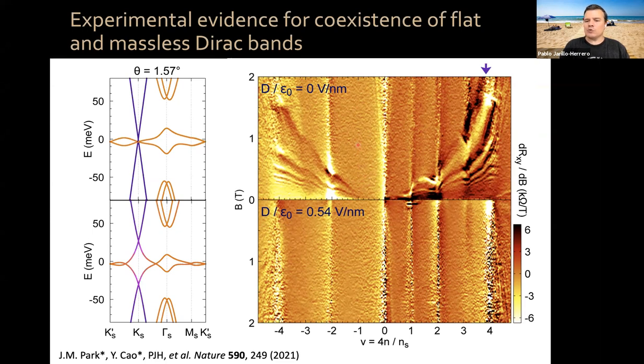At finite temperature, you do see a feature that corresponds to correlations at nu equals minus one, okay? But that's at finite temperature. At the lowest temperatures in transport, we don't see anything, typically. In RxX, you see a little bit of a feature in RxY sometimes, okay? But here actually I'm showing RxY, so it's not there. There's a weak thing, which is effectively compressibility, but it's rarely present. So that's consistent with what we'd expect from bilayer graphene.